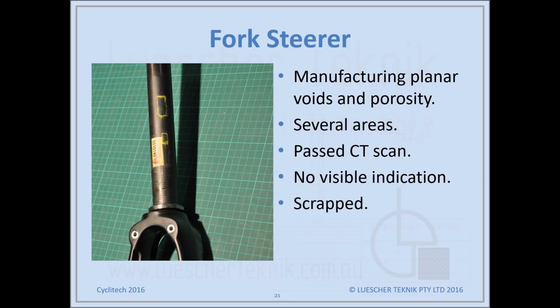So another fork steerer, and you can see several areas marked in the yellow crayon there, where we found again some planar voids. Now this had passed a CT scan, and there was no visible indication of any flaw on the surface,